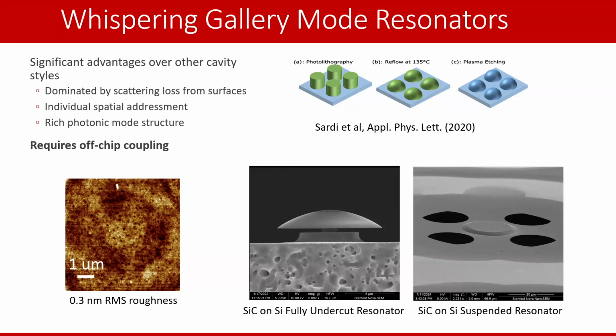And so that means this photoresist reflow process that I just mentioned, because this causes the photoresist to melt. The melted photoresist then has an extremely smooth surface. So when you use your reactive ion etch to transfer the pattern, you transfer the extremely smooth reflowed surface into the already relatively smooth silicon carbide. You maintain the surface roughness from the original CMP polishing step. And so from that, we've made several whispering gallery mode resonator designs. You see this mushroom here that's completely undercut, as well as this semicircle here that's suspended.